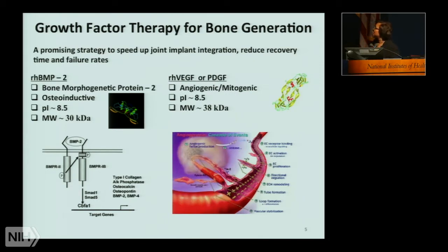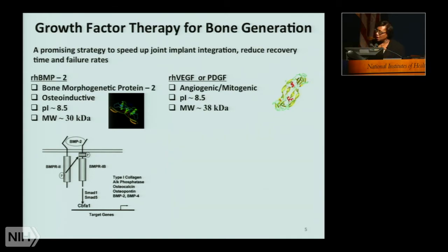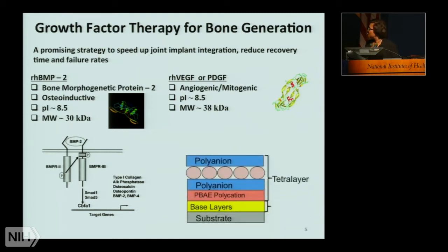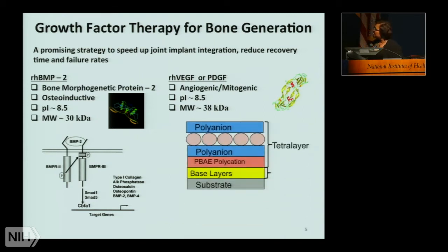We're also interested in growth factors that can support vascularization. And some of these include VEGF, which is a direct angiogenic factor, and platelet-derived growth factor, PDGF, which is mitogenic, but also supports the generation of the vascular system. So these are proteins that are similar. You notice that they all have an isoelectric point of 8.5. That means that in water at pH 7 or neutral pH, they're positively charged. So we treat them as a positively charged entity.